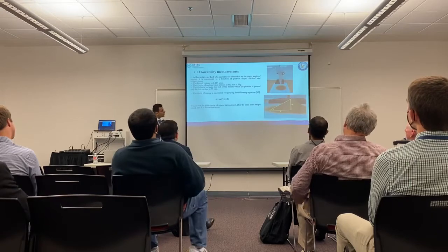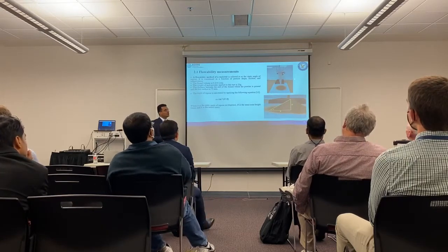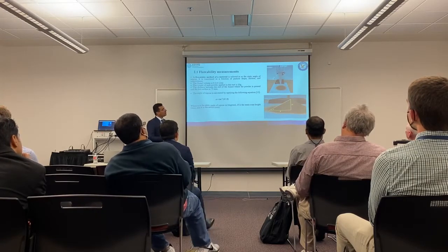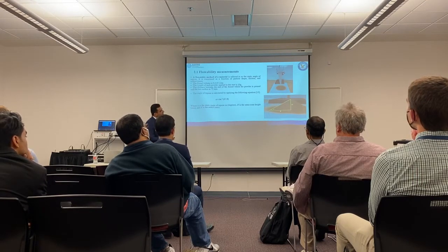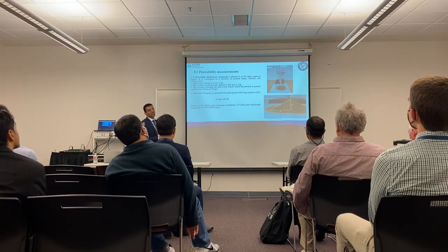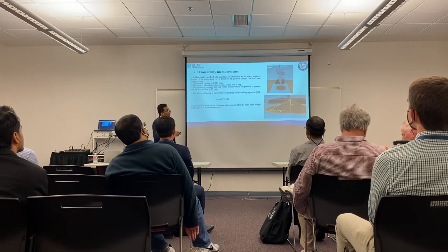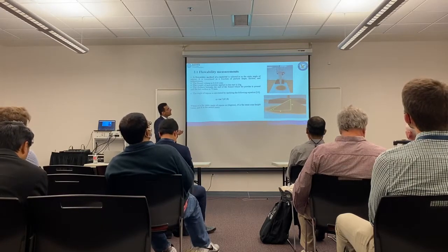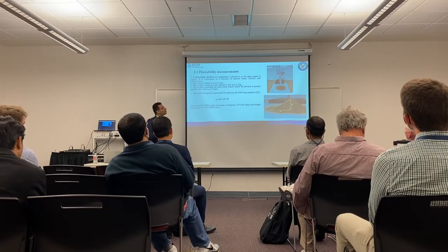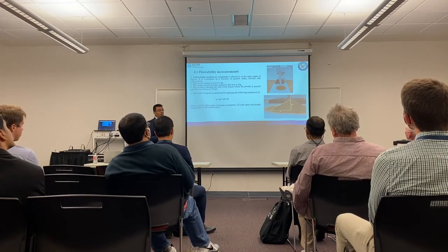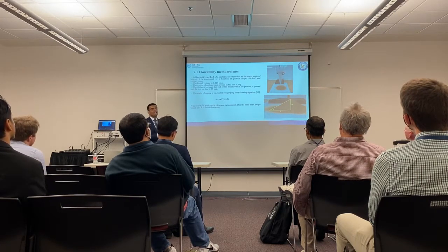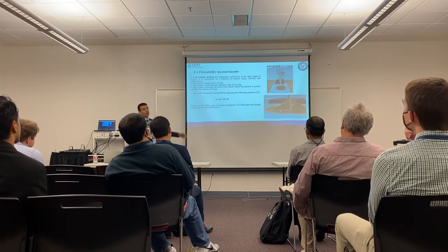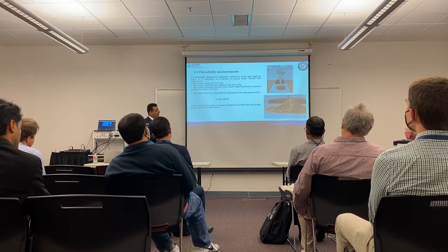Another physical property we measured is flowability. Actually, we installed this device, with a volume of 0.21 liter, and the distance between the end of this funnel and the test surface was 75 millimeters. We pour the powder into the upper stage of the funnel, and it is smoothly and continuously distributed to get a heap of conical shape. Then we could measure the height and radius of this heap. After that, we apply alpha equals tan inverse of h divided by r to get the angle of repose for each one. Also, we ran this 5 times for each powder.